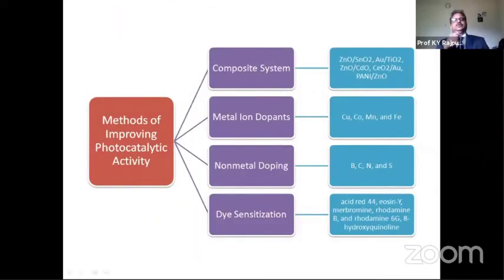One way in which the photocatalytic activity can be improved is to make a composite system. For example, TiO2 has a band gap of around 3 electron volt, so for using TiO2 as a catalyst, you need UV light. And for example, you have tungsten trioxide or other compounds whose band gap lies in the visible, so you need visible light for degradation. If you make a composite between these two materials, then it is possible to harness the whole solar spectrum for catalysis.